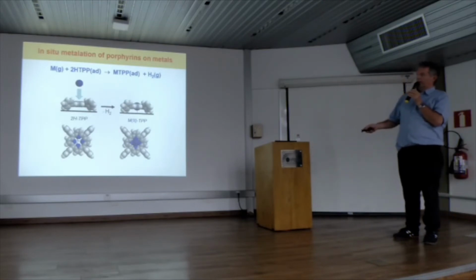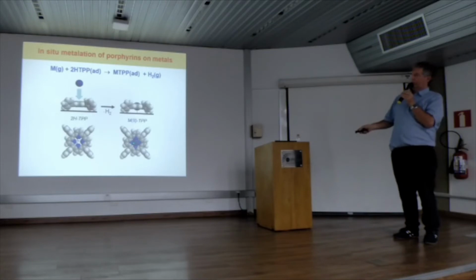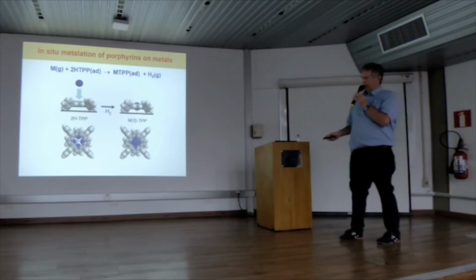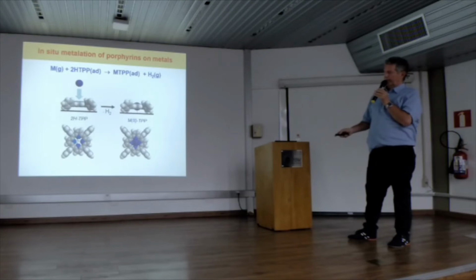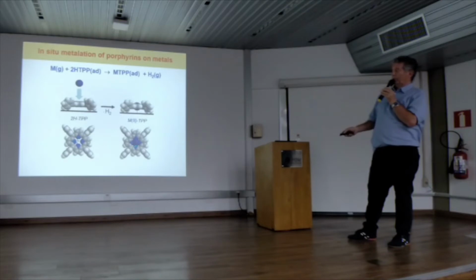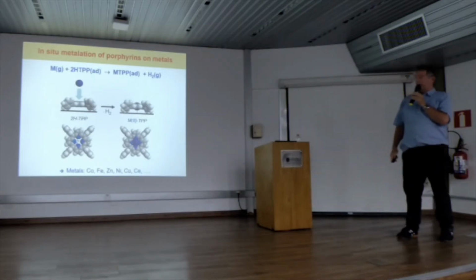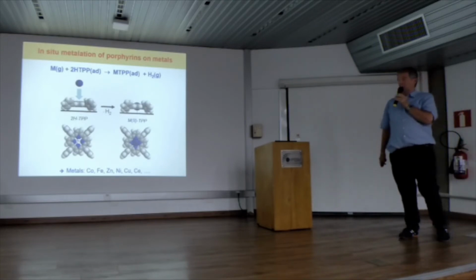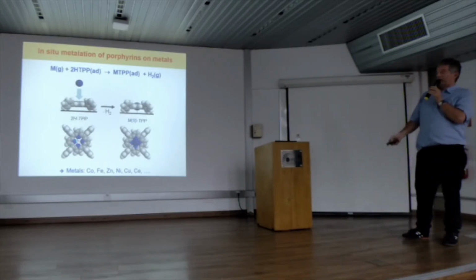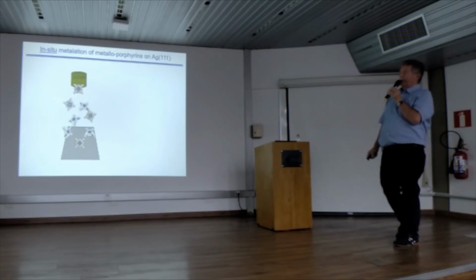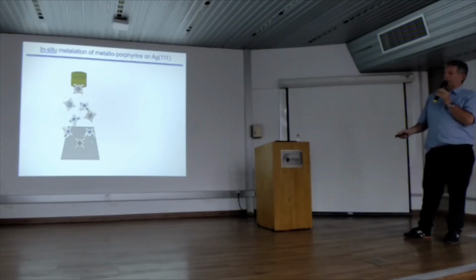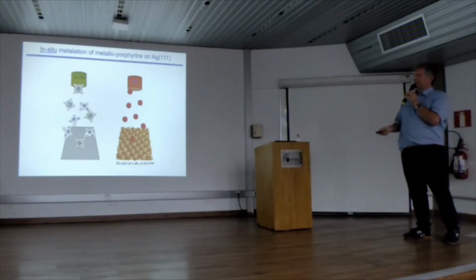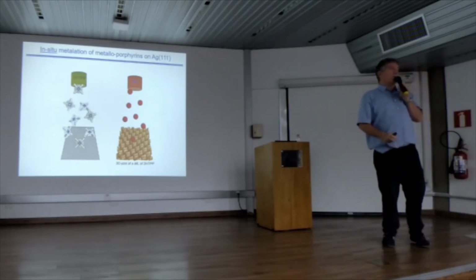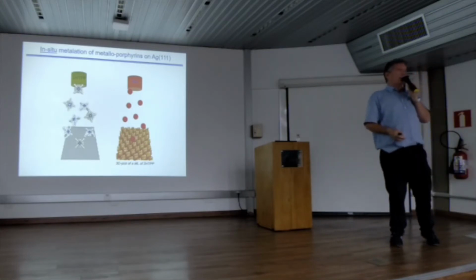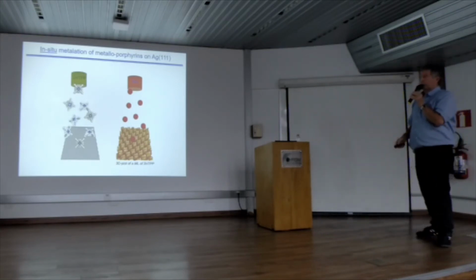So there's no molecule in the pocket, you add a metal atom, then you get the metalloporphyrin. Very importantly, if you look now at our nitrogen atoms, these are inequivalent, and these are equivalent now. So here we should have 2 peaks, here we should have only 1 peak. And this is exact, and you can do that with many, many different metal atoms. And the signature of the nitrogen atoms is typically what we do to identify. The process is very simple. You deposit the porphyrin, you deposit the metal, and it turns out that for most systems, and particularly if you use some additional heating, you get the same result. So it doesn't matter what you put down first.